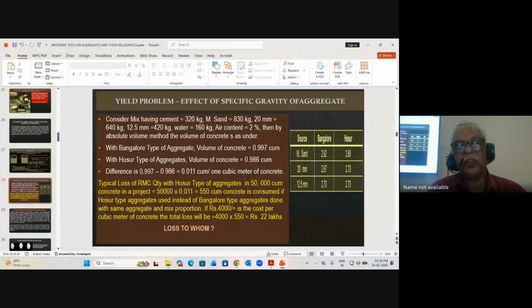Suppose there is 50,000 cubic meter of concrete used in the project. The difference can be about 550 cubic meter. So you are paying for 550 cubic meter extra by switching over to Hosur type of aggregate, which has got a higher specific gravity of aggregate. So there is a loss to be considered.